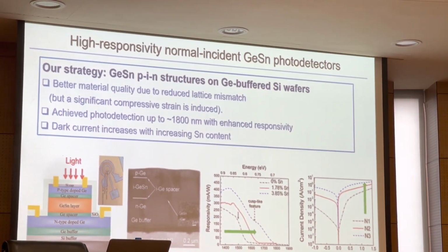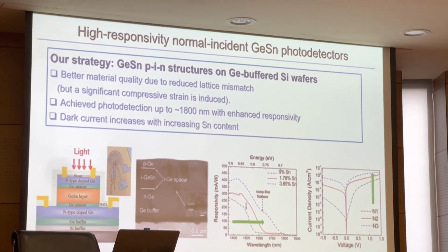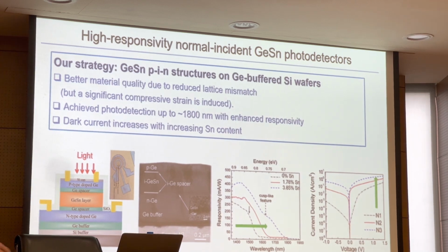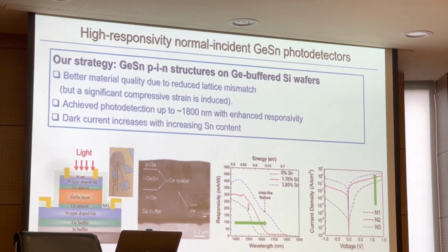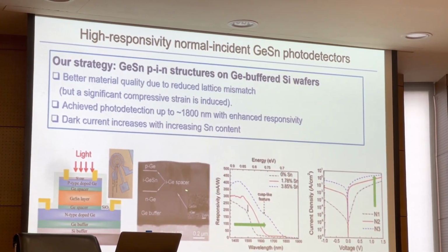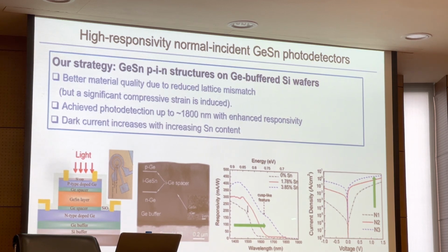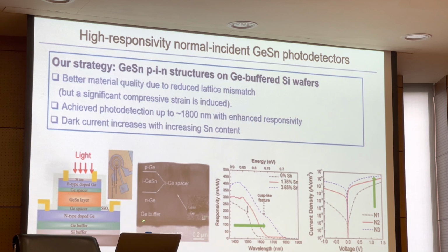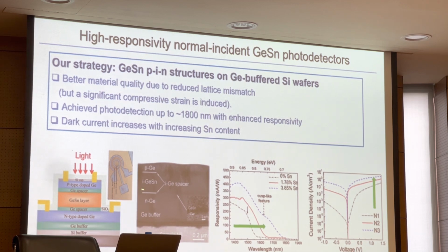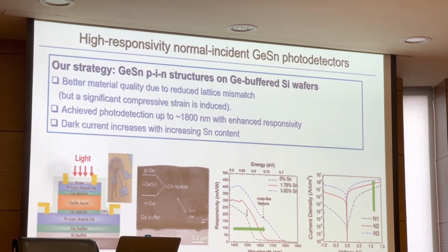We grow our GeSn layer on the germanium buffer layer first, so we can confine the defects at the interface of the germanium and silicon layer. So the material quality in our GeSn layers actually improves.